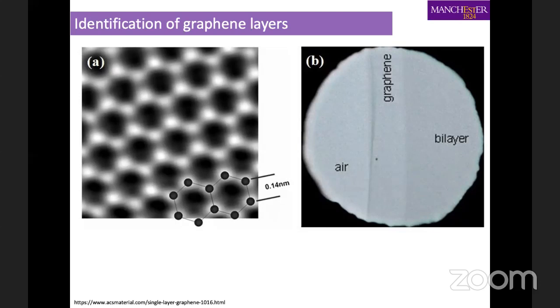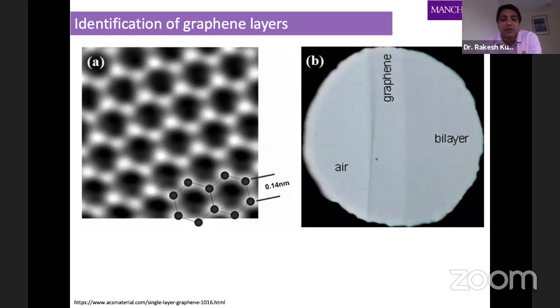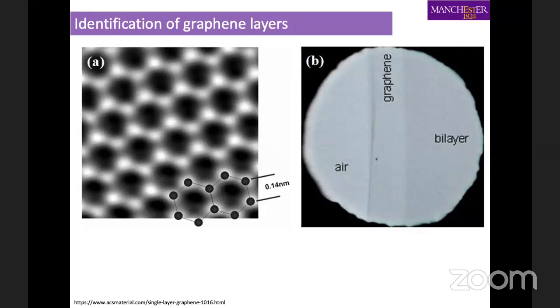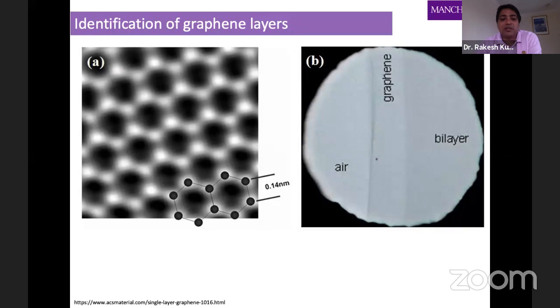And if we go to a single atom film, you can zoom in and see these bright spots. These bright spots are the atoms and the electron clouds. The distance between each atom cloud is around 0.14 nanometer, which is the bond length. So these are the highly sophisticated tools used to identify graphene on solid surfaces.